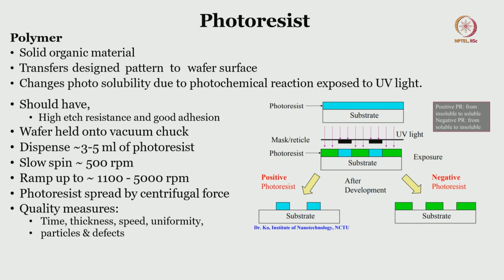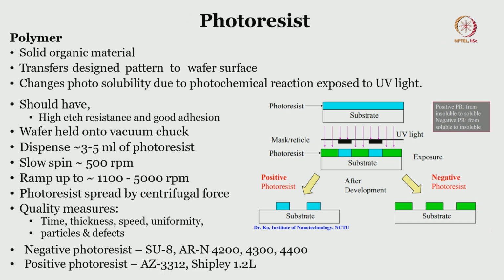How it is done? So, the wafer is held onto the vacuum chuck. We dispense about 3 to 5 ml of photoresist. First we start with a slow spin, so that a uniform coating is there, then you ramp up the speed depending on what kind of thickness you desire for the photoresist. It is spread by centrifugal force, and the quality measures are time, thickness, speed, uniformity, and some of the defects are particles that are there on the wafer. These are some of the negative photoresists and some of the positive photoresists. Nothing to really remember here, because if you Google it, you will find different photoresist data sheets, where to buy, and everything else.